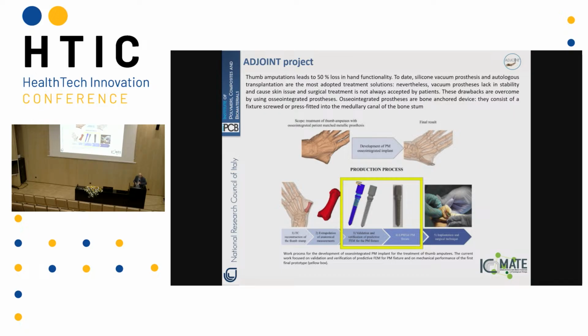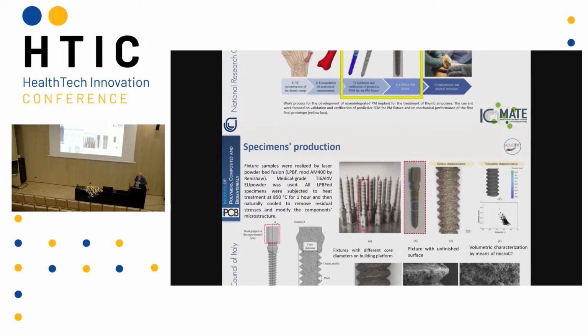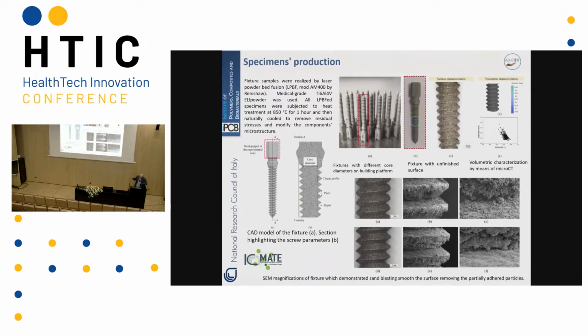The people that want to use it have to use a material that comes from odontoiatric application. So you can understand that you don't have the right dimension of this object, and there are also problems of compatibility with the system. Okay, my colleague that works with the metals made a lot of tests by changing the direction of growth, changing the materials, changing the structure. For example, I remember at the beginning they started with a very complex internal geometry with lattice geometry and Voronoi and so on. But at the end, what we found was that the best result was a standard closed geometry.